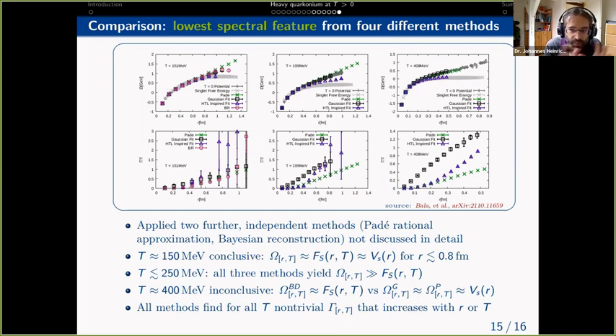And so one of the problems with the screening is the question whether the quark anti-quark pair has enough time to rearrange according to some modified interaction, or whether it dissociates and decouples before it could rearrange according to a modified potential. I think that is one of the ways to phrase it: apparently the dissociation happens much faster than the time that would be needed to rearrange. And of course, with a singlet free energy, we consider the static case, and there we have as much time as we like.